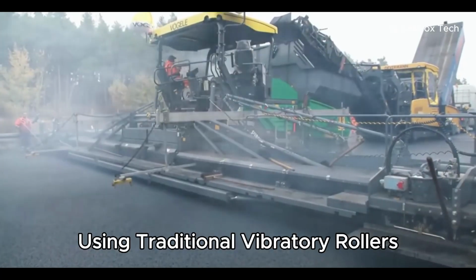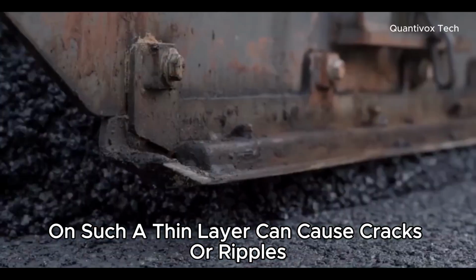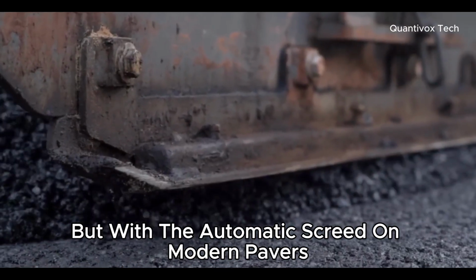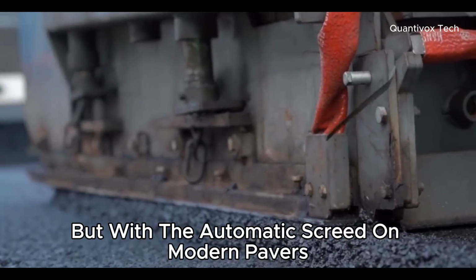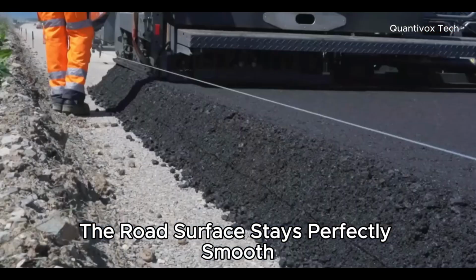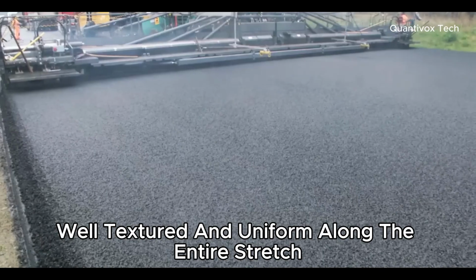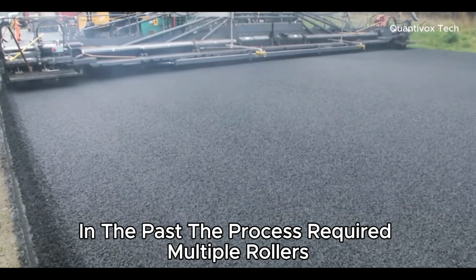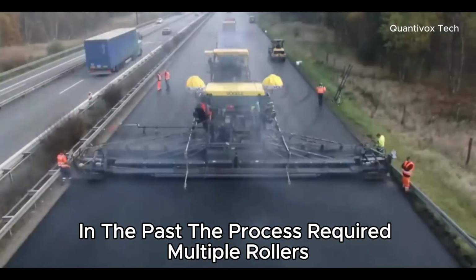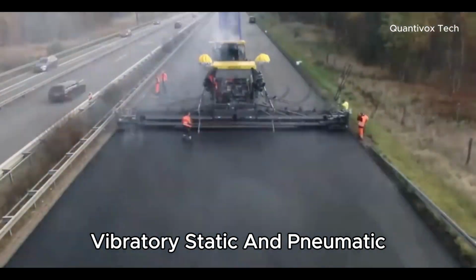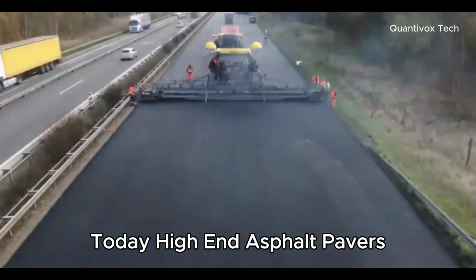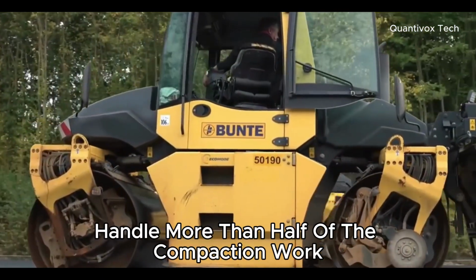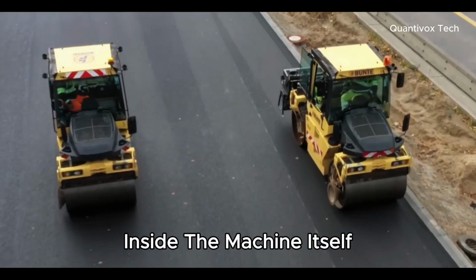Using traditional vibratory rollers on such a thin layer can cause cracks or ripples, but with the automatic screed on modern pavers, the road surface stays perfectly smooth, well-textured, and uniform along the entire stretch. In the past, the process required multiple rollers, vibratory, static, and pneumatic, to achieve the proper density. Today, high-end asphalt pavers handle more than half of the compaction work inside the machine itself.